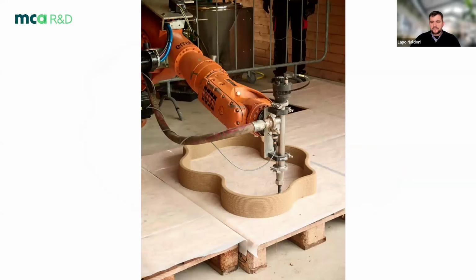So as you can see, we started testing the system on the island, and we designed this shape of the blocks in order to help the stability of the material during the process. So the limitation of those blocks was the weight, because everything must be assembled by hand without machinery. And the second point is that we use lime-based mortar. The lime during the process is really unstable, and to increase the stability of this material, we designed these waved blocks, and all those waves help the stability during the printing process.